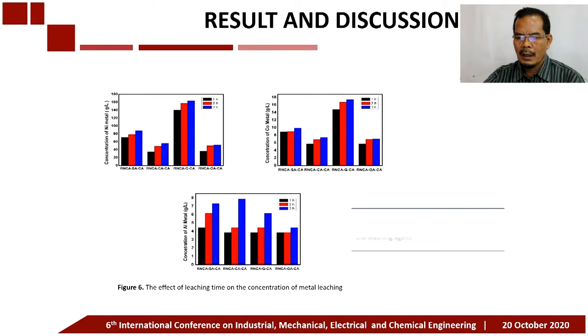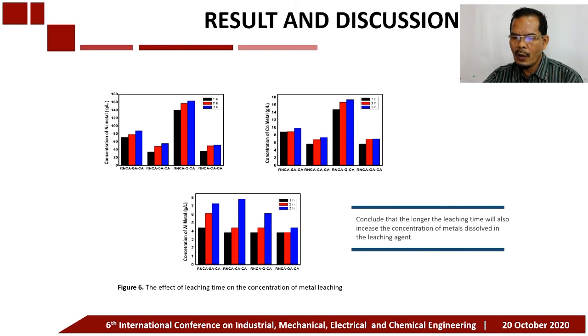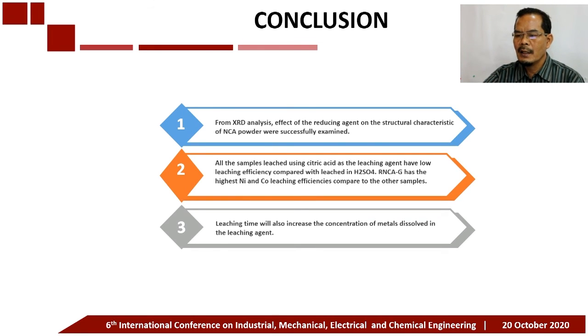Okay, we come to the effect of leaching time. Leaching efficiency increases for all samples, using either organic or inorganic acid as the leaching agent. In other words, the longer the leaching time, the higher the metal leached in the leaching process. The difference in concentration between leaching times of 2 and 3 is quite small. It can be said that the longer the leaching time, the higher the concentration of metal dissolved in the leaching agent.